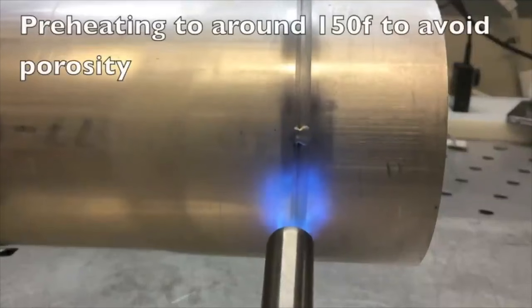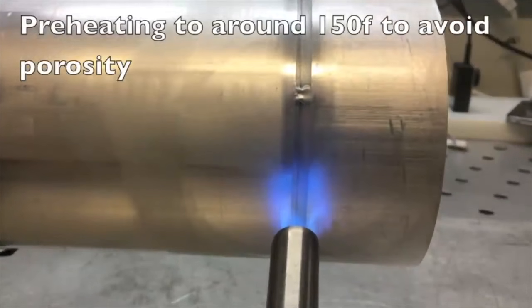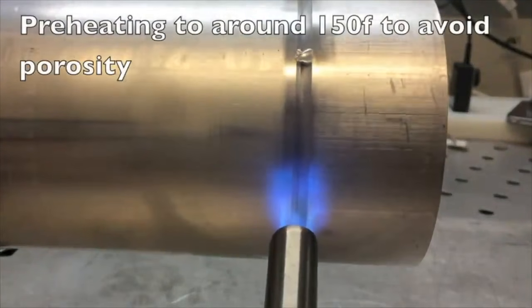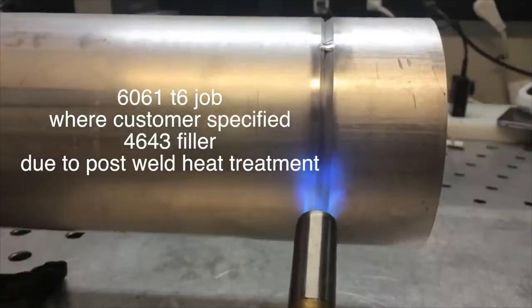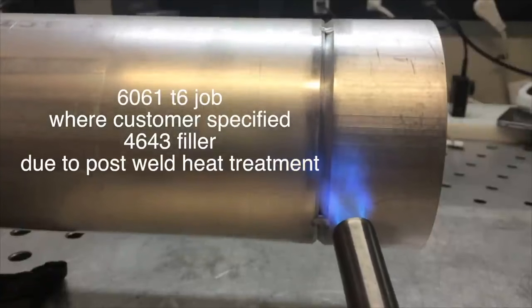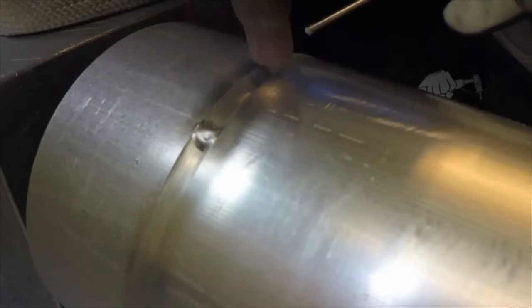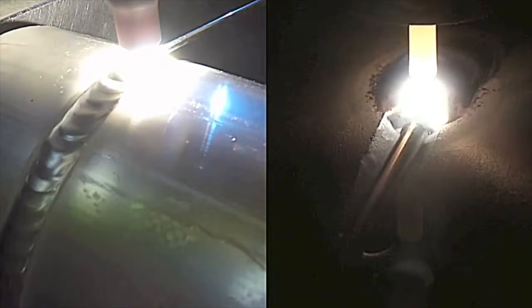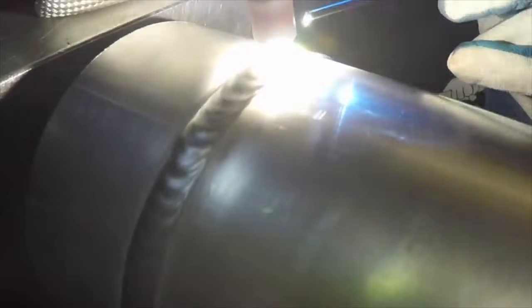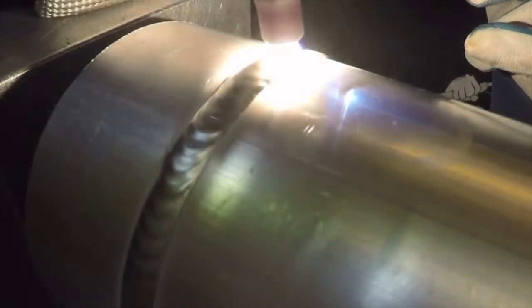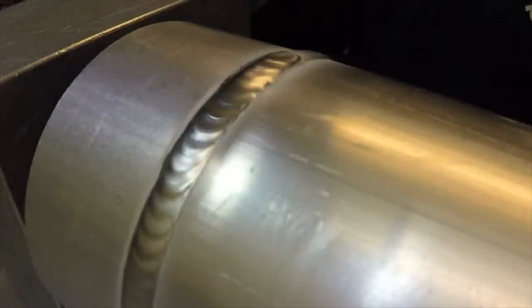Here's an example of a job that my friend Roy Crumrine did of a 6061 hydraulic tube that was welded with different filler metal than usual so that it could be heat treated, and so that the filler metal would respond to heat treatment as well as the base metal. A low preheat of 150 degrees was used just to prevent porosity and to drive off moisture a little bit. For heat treatable aluminums like 6061, it's recommended that you don't go much over 200 degrees for a preheat, otherwise you can lose strength in the heat affected zone.